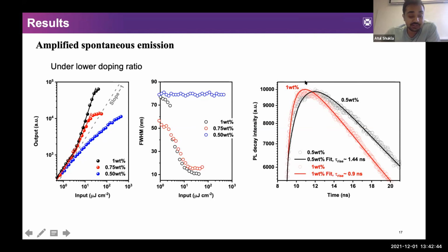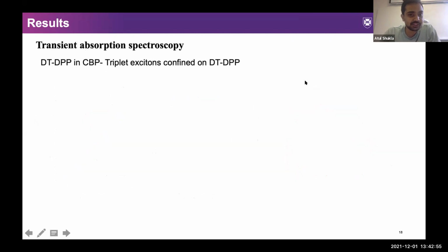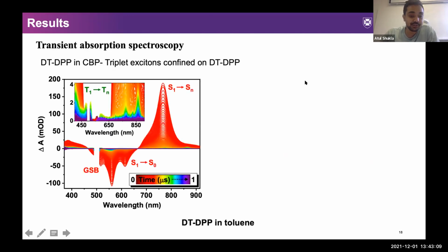So these results were really good, but we also wanted to study if triplet excitons are leading to losses in this system. So we did some transient absorption spectroscopy to get an estimation of the triplet absorption band, because that shows how much the TTA would impact our devices under electrical pumping. So this shows the transient absorption signals at different time delays. And we can see the triplet absorption band here.